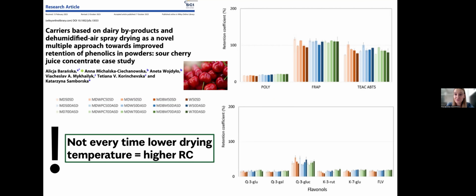because as you can see over here on the right on these figures with polyphenolics and flavonols at the bottom, you won't see any really significant differences with retention coefficient. It doesn't matter the carrier content or drying method. So this really highlights the complexity of the spray drying process, and definitely this is why there is the need for further systematic research. Definitely what really happens during the spray drying, that even though we are lowering the drying temperature, is why we do not see the higher retention coefficient, especially when we are excluding the carrier from the calculations.